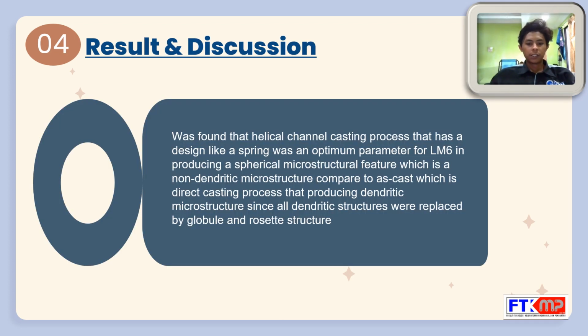In this present investigation, it was found that the helical channel casting process that has a design like a spring was an optimal parameter for LMC in producing a globular microstructure feature, which is a non-dendritic microstructure, compared to as-cast, which is the direct casting process that produces the dendritic microstructure, since all the dendritic structures were replaced by globular and rosette structures. This new design helical channel that has a spring shape has a strong influence in the formation of globular microstructure of LMC aluminium alloy.